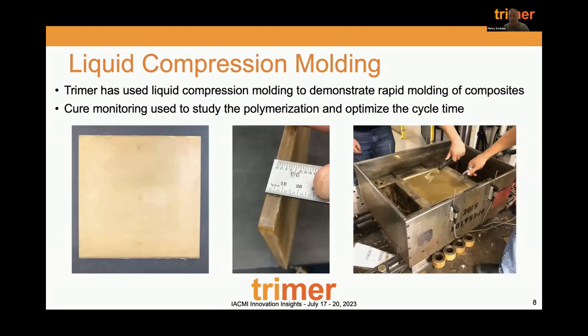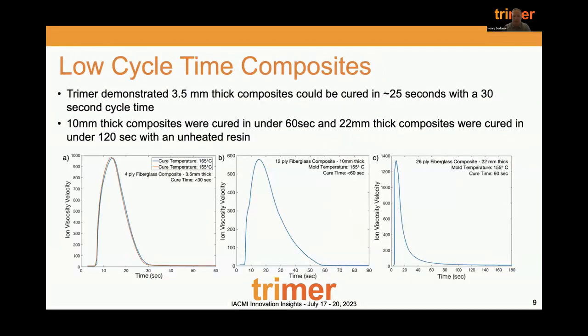Just to show you this high rate manufacturing, really one of the novel features of our material. Our slowest resin system cures in about 20 minutes, and that's the slowest. Our fastest resin systems cure much quicker. So this is just to show a liquid compression molding application. It's a steel tool and a closed die. What we have here is these plots showing ion viscosity. It's essentially dielectric loss. It's monitoring the ion mobility in the polymer.